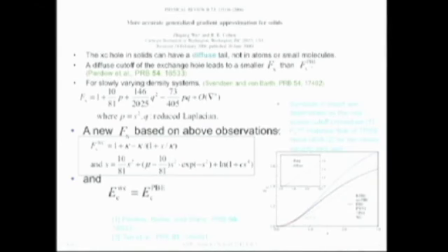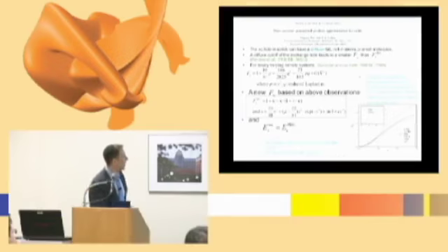And if you have an ionic insulator like lead titanate, there's a lot of empty space in it, so there's a lot of tails. Since the atoms are very polarizable, like the lead and the oxygen, and it's a ferroelectric, the atoms want to move off-center. If you don't treat those regions of low density right, you get really disastrous problems.